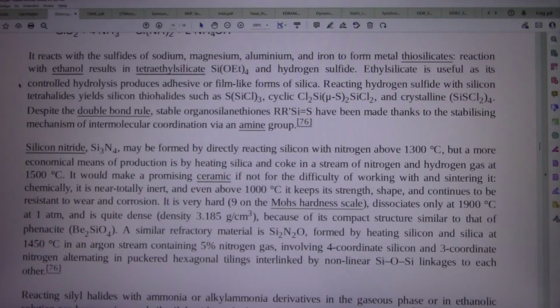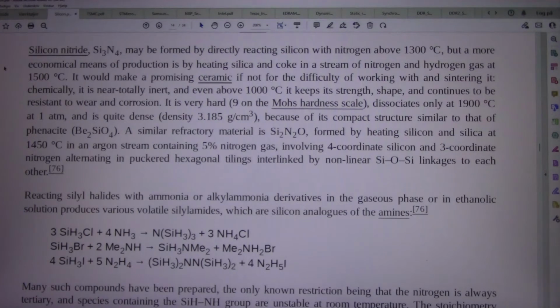76. Silicon nitride, Si3N4, may be formed by directly reacting silicon with nitrogen above 1300 degrees Celsius, but a more economical means of production is by heating silica and coke in a stream of nitrogen and hydrogen gas at 1500 degrees C. It would make a promising ceramic if not for the difficulty of working with and sintering it chemically. It is near totally inert, and even above 1000 degrees Celsius it keeps its strength, shape, and continues to resist wear and corrosion. It is very hard, 9 on the Mohs hardness scale, dissociates only at 1900 degrees Celsius,